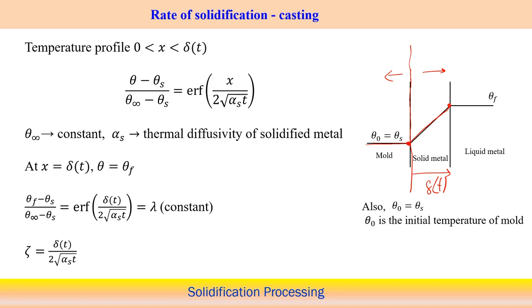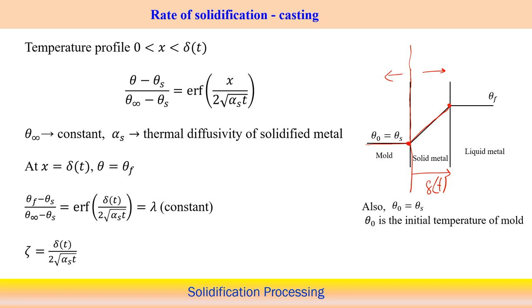Whatever is variable is theta, and it depends on the distance x. I think you are familiar with this error function, because when we discussed sand mold casting, the heat transfer through the mold wall, we explained that by utilizing the error function we can calculate the rate of heat conduction along the mold wall. A similar error function we are utilizing here to understand the heat transfer phenomena in this particular case. Here theta infinity is constant, and alpha is the thermal diffusivity of the solidified metal.